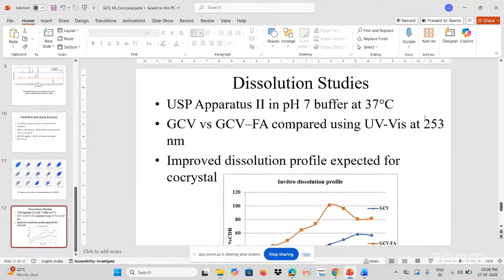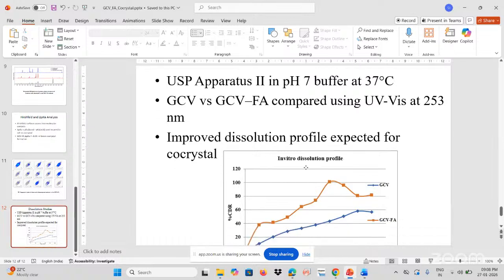If we see this slide particularly, here we can see the different interactions which have taken place: CC bond, CO bond, CH bond, CN bond and the OH bond. If you observe here, it is the OH bond, the hydrogen bond, that is showing the major contribution because of which crystal packing has taken place. So after getting the confirmation from Hirshfeld, single crystal XRD, pKa analysis, FTIR and DSC, we went further for the dissolution study, in which we used the USP apparatus with pH 7 buffer. And here you can see the improved solubility.